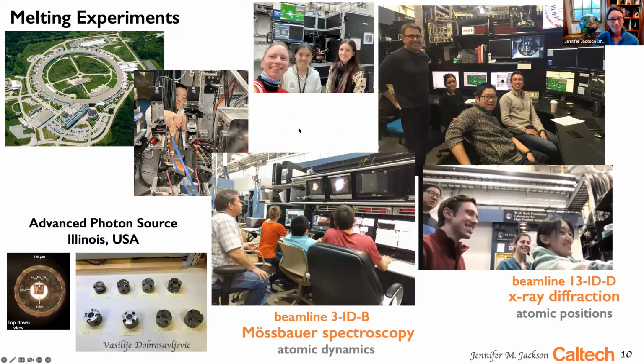Here is an array of pictures from many of the experiments that we've been conducting. So all melting experiments that are shown here today were conducted at the Advanced Photon Source at two different beamlines. The Mössbauer spectroscopy measurements were conducted at 3-ID-B, and the X-ray diffraction experiments were conducted at GSECARS 13-ID-D. Shown here is a typical sample loading environment of the sample surrounded by a potassium chloride thermal insulator, as well as a fleet of diamond anvil cells that we typically take to conduct these experiments.